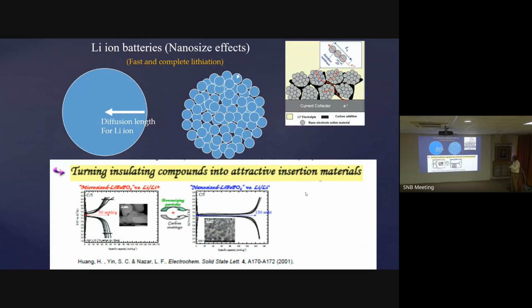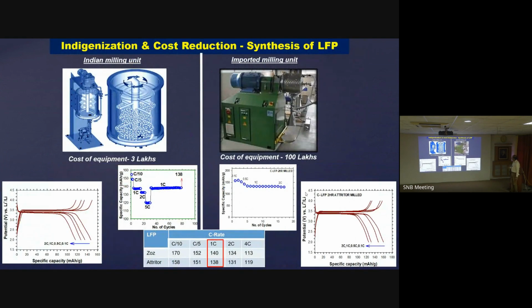I already told you that the nano size helps by decreasing the diffusion length, so your charge and discharge become very fast. Initially we used a high energy milling machine, where you take all the raw materials, lithium carbonate and iron oxalate, and some additives to have a robust carbon, which is the key process for which we filed a patent, and ammonium dihydrogen phosphate. You mix these at atomic scale, that means real mixing, so that your reaction is much more homogeneous and you don't have any impurity phase in your LFP.